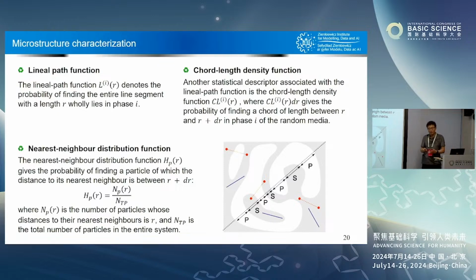And this matters for some materials, say porous material in particular, the connectivity between phases. Water: to understand how water passes through your sponge, the direction of your pore space doesn't help. You need to know the connectivity, and that's where the lineal path function comes into play.